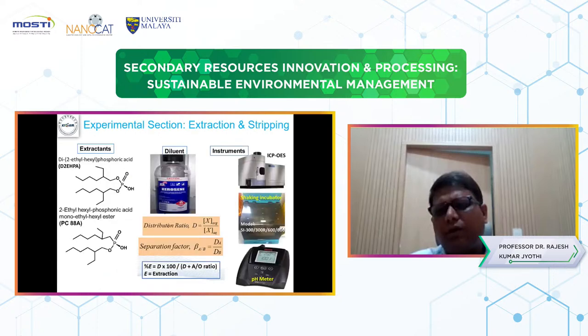The scientific experimental approach we applied used commercial extractants like di-2-ethylhexyl phosphoric acid and 2-ethylhexyl phosphonic acid mono-2-ethylhexyl ester. We tested two reagents using a kerosene diluent, and the instruments we used here are ICP-OES, a shaking incubator, and a pH meter.